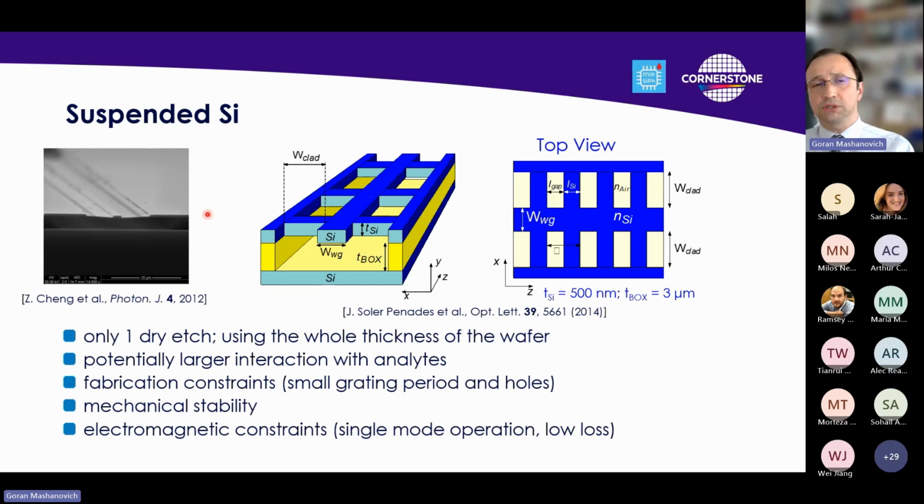And we can take two approaches. One, where we etch rib waveguide. So we form first the waveguide. And then we etch these holes, which are relatively far away from the waveguide, such that the optical mode is not disturbed. And then we use these openings, these holes, to remove the oxide underneath. So we can suspend this, and this is work from Hon Ki Tsang's group in Hong Kong, where they demonstrated these suspended silicon waveguides at a wavelength of 2.75 microns.